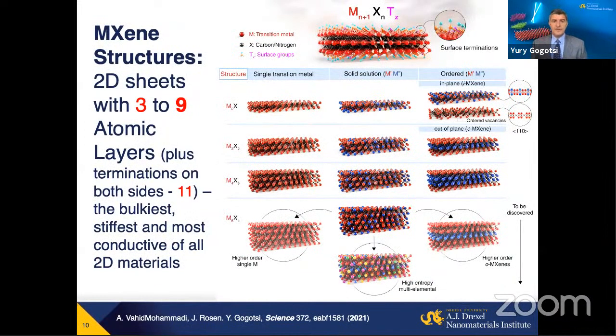Now, what do we have today, 10 years after this first discovery of Ti3C2 MXene? We have a large number of structures: M2X, M3X2, M4X3, M5X4. So actually, those are the thickest two-dimensional materials. Each of these blocks, which is just a little bit thicker than a nanometer, is well-defined, has exactly the same composition, same thickness. But unlike graphene, which is flimsy, those are rigid. Bending rigidity is orders of magnitude higher than graphene. So you can construct very thin devices, self-supported films here.